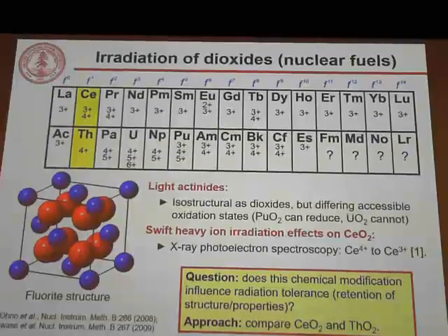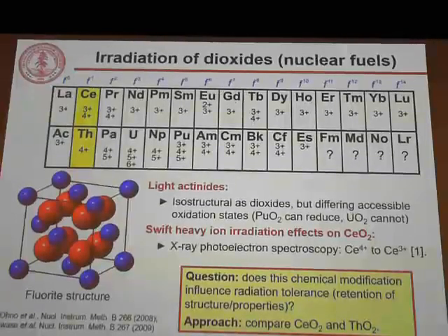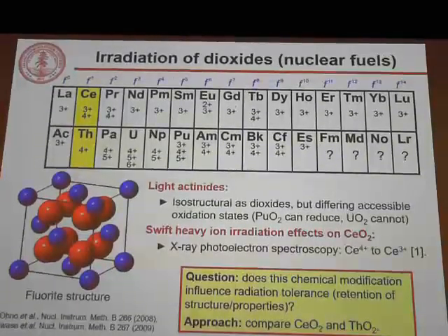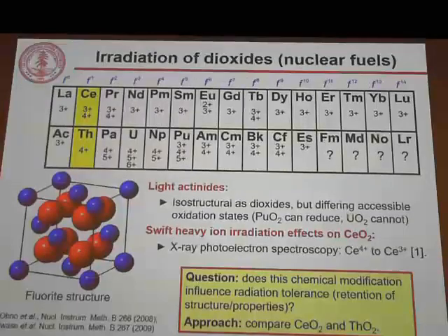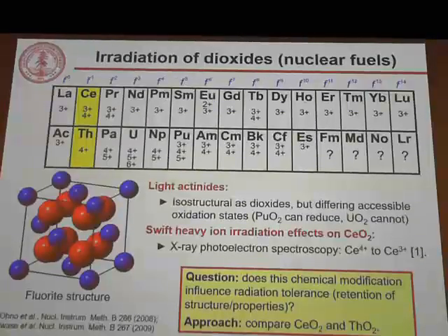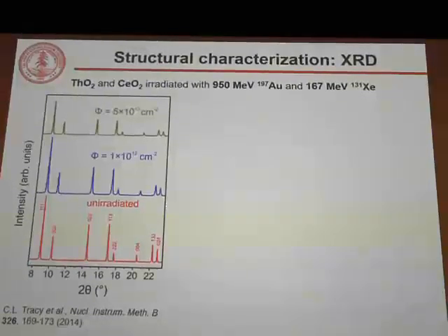To answer this, I compared mainly 2 materials, cerium dioxide and thorium dioxide. Now, these are nice model systems because they have very similar thermophysical properties, the same fluorite structure, nominally 1 f electron in the cations. However, they differ in one main respect. Thorium has only a tetravalent oxidation state. Cerium has an easily accessible trivalent oxidation state. So by studying these, we can really isolate any effects of this irradiation-induced redox behavior. So I first irradiated these materials with some different ion energies, different ion masses, and then characterized the structural changes using X-ray diffraction, which I show here, starting with the unirradiated sample at the bottom and an XRD pattern of increasing ion fluence as we move up.